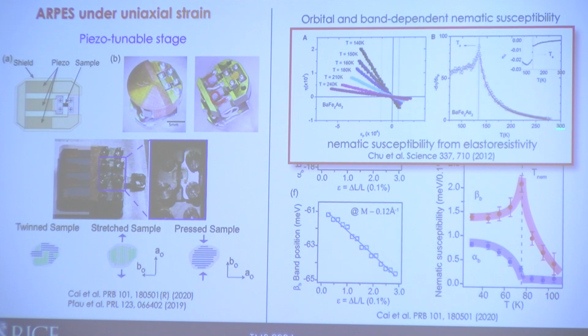This is one of the first evidence that this is an electronic nematic order in the iron pnictides from transport measurements. But you can see now that if you're able to do this kind of continuous strain with photoemission, then you can have additional information about this with the momentum structure. So I think this is a very promising way to look at nematic order for materials beyond the iron pnictides. Something we're currently using this for is to look at the superconducting dome region of the iron pnictides, to try to understand the effect of nematic susceptibility near the superconducting dome. Anyway, so this is the second aspect.